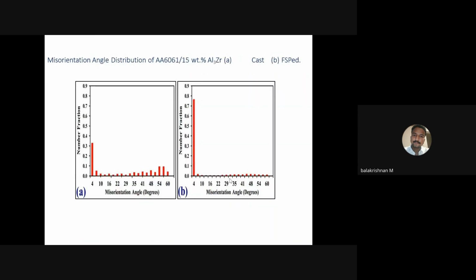Then misorientation angle distribution compared to cast, it is somewhat lower because the particles are finely refined by the tool rotation, that is, three-dimensional flow of material. At the same time, the forging pressure will act to refine the particles. At the same time, the material will not come out of the shoulder diameter of the tool. So the refinement will happen very fine compared to other secondary processes.